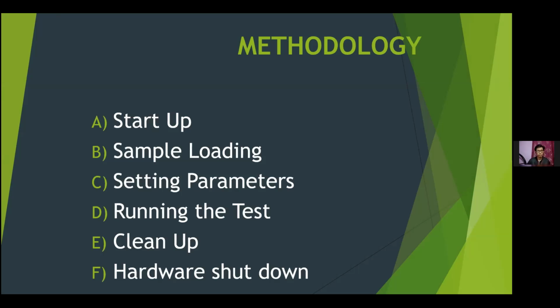The first step is the scale, a Tzero hermetic lid and a Tzero pan were placed on the balance. Third, the balance door was closed and we waited until the balance stabilized before recording the weight. One drop, approximately 3 to 6 milligrams of each sample, was pipetted into the aluminum pan using a disposable pressure pipette. Using tweezers, the pan was placed in the blue T0 hermetic lower die and the die put into the Tzero. The lid was placed on top of the pan using forceps.